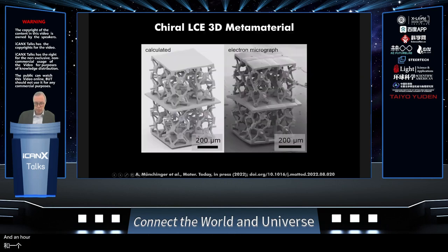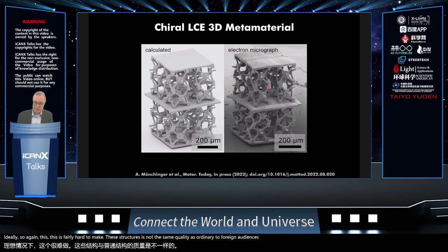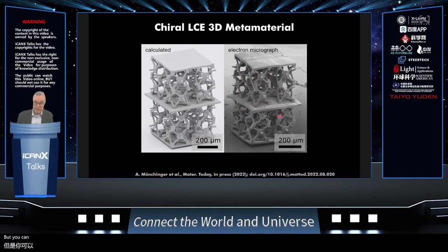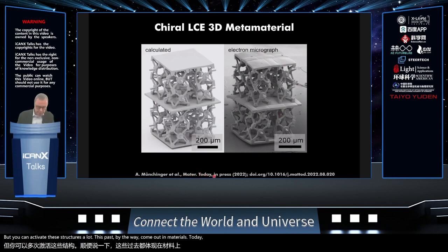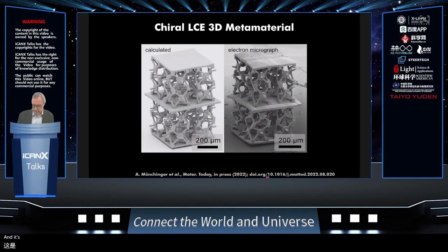And I now show you the same thing for the chiral metamaterial, which is a much more complex structure yet. This is the measured electron micrograph. This is a rendering of how it should look like ideally. So again, this is fairly hard to make these structures. It's not the same quality as ordinary two-photon or two-step laser printing, but you can actuate these structures a lot. This has, by the way, come out in Materials Today a few weeks ago. It's available online, but it has not been printed yet.